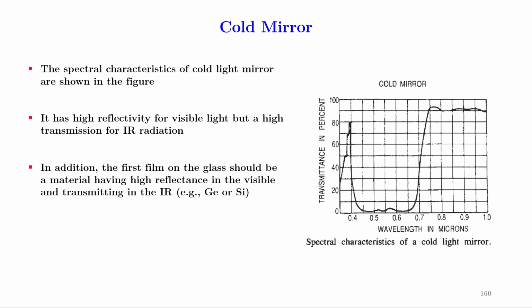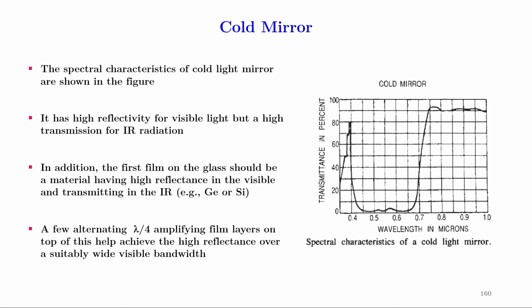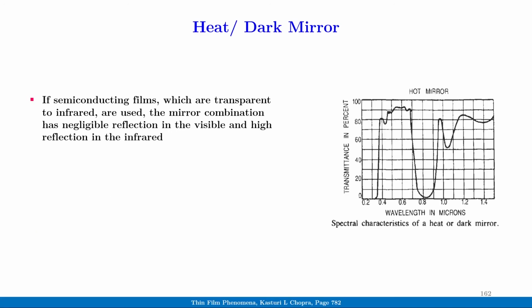In addition, the first film on the glass should be a material having high reflectance in the visible and transmitting in the IR, for example germanium or silicon. A few alternating lambda 0 by 4 amplifying film layers on top of this help achieve the high reflectance over a suitably wide visible bandwidth. If semiconducting films which are transparent to infrared are used, the mirror combination has negligible reflection in the visible and high reflection in the infrared. Such a system is called a heat mirror or a dark mirror.